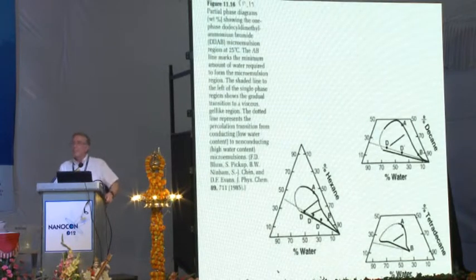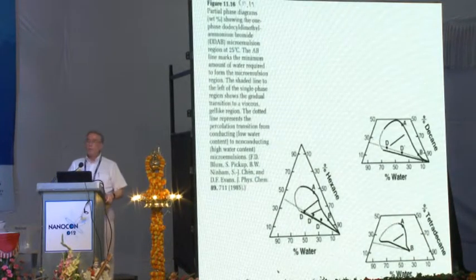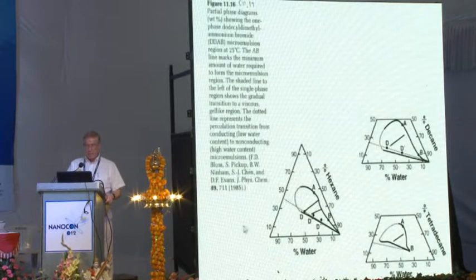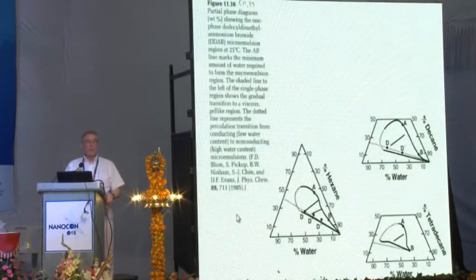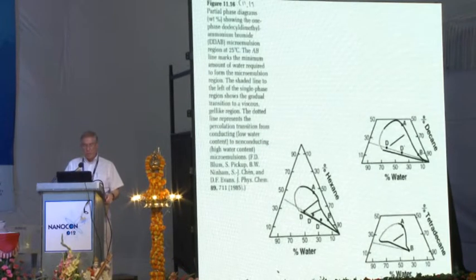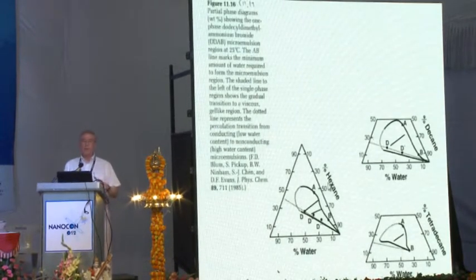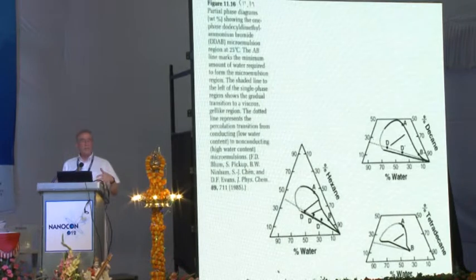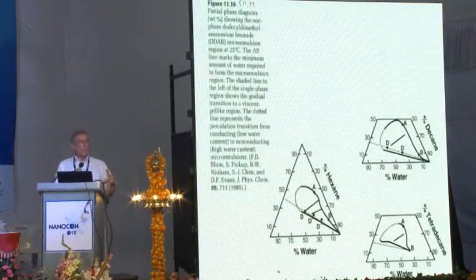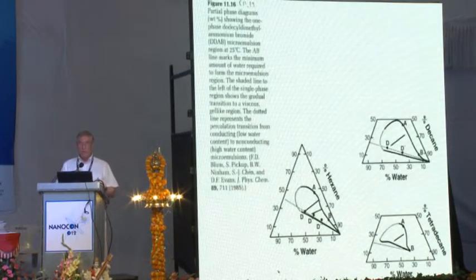Another example is here. It's an old problem. It's a problem that has been in the literature for 25 years. It was a system that was studied by two giants of colloid science, Barry Ninham and Fennel Evans, and they found out that if they take a double-chain surfactant, didodecyl dimethyl ammonium bromide, and mix it with water and with oils, different oils, at the right proportions, they get large domains of microemulsions. But they did something else.